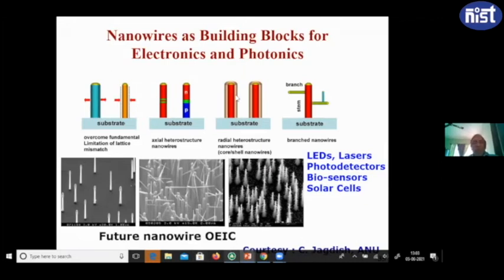Okay, this slide I have taken from Professor Jagdish, who was my friend at Australian National University. This is a schematic of the nanowire. He grows indium phosphide and gallium arsenide nanowires for making lasers, LEDs, photodetectors, biosensors and solar cells. The advantage is that during the growth of the nanowire, you can make a p-n junction also. You see, this is p and this is I, I means intrinsic, and you can dope it.